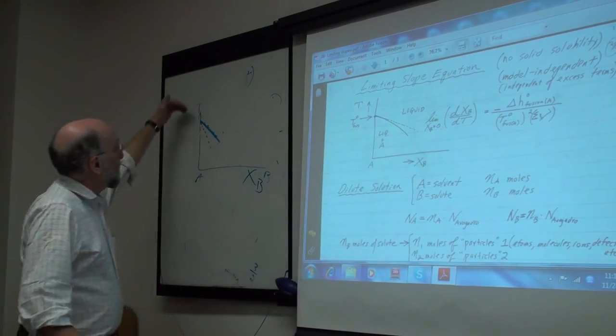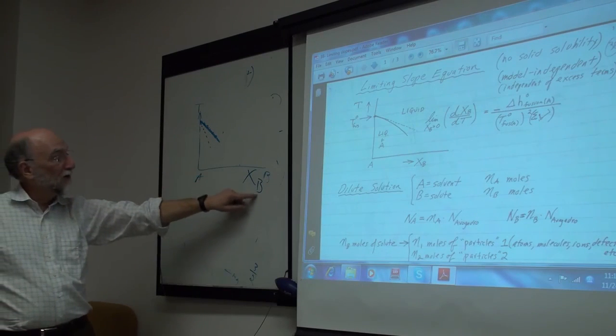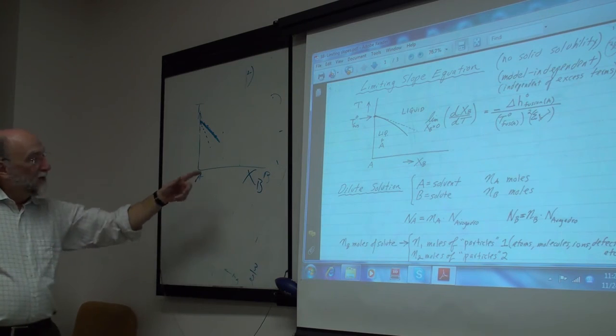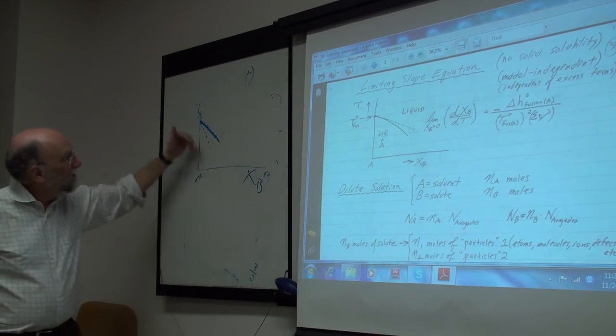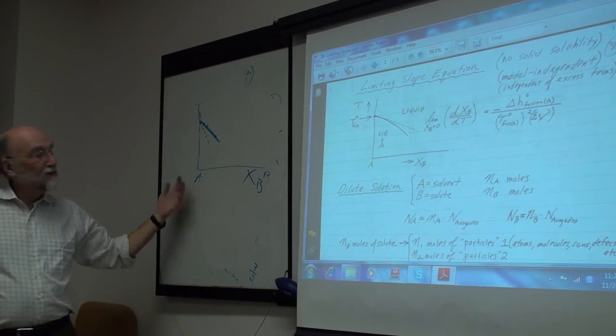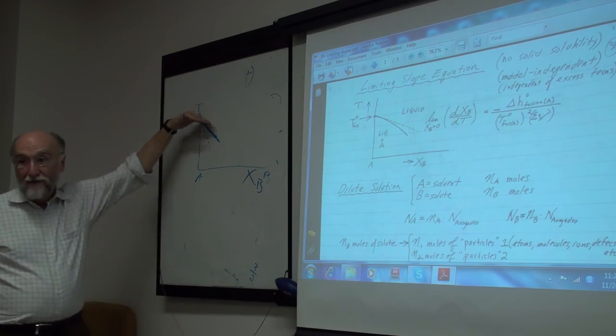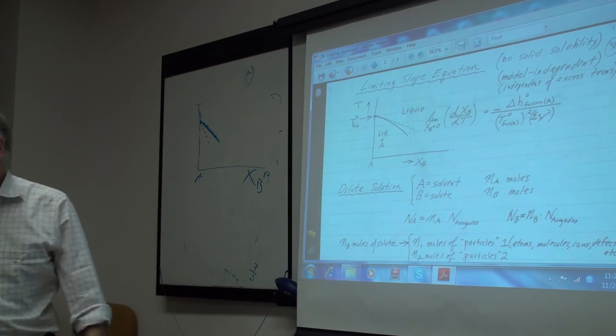If the liquidus is below, that would indicate that sigma nu was greater. If you calculate this for a number of foreign particles equal to 1, for a metal, you know it can't be greater than 1, so there's no way that 1 mole of nickel is going to give you 2 moles of nickel. And always, solid solubility will always raise the liquidus.